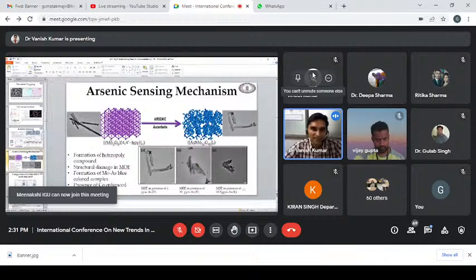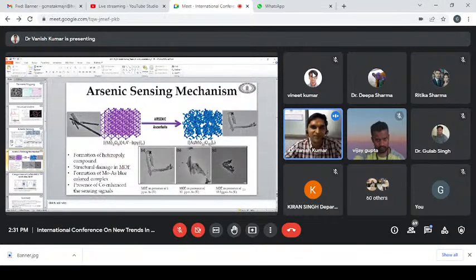So what was the sensing mechanism? As shown in this purple colored image, this is the MOF. I'm not including cobalt here because the interaction is specifically between the molybdenum and arsenic. But cobalt is playing a good role as a catalyst. Due to the catalytic properties of cobalt, molybdenum readily interacts with the arsenic to form this heteropoly compound, an arsenic molybdenum oxygen compound, and after formation of this arsenic molybdenum complex, the structure of the MOF was degraded.